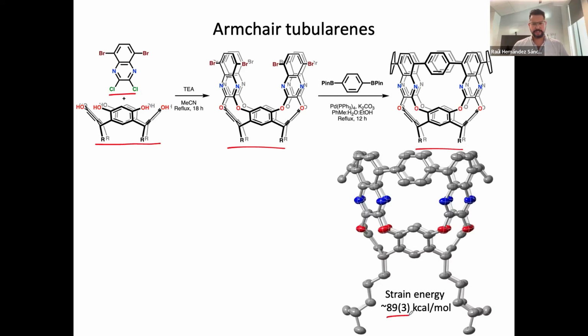DFT calculations tell us that it has about 90 kcal per mole of strain energy. Now, to put that in perspective, a C-H bond in methane has a bond dissociation energy of 104 kcal per mole, right? That is the bond dissociation energy. Here we have a compound with 90 kcal per mole of just strain, mechanical strain, by distorting the aromatic system.